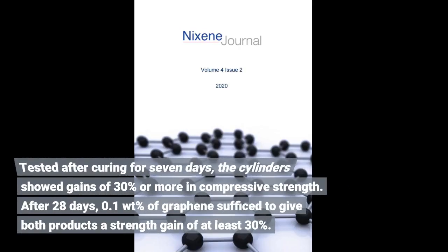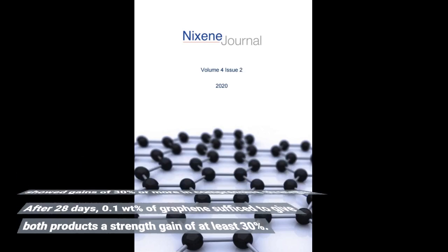Tested after curing for 7 days, the cylinders showed gains of 30% or more in compressive strength. After 28 days, 0.1 Wt% of graphene sufficed to give both products a strength gain of at least 30%. This increase in strength is in part due to a seeding effect of 2D graphene for better growth of cement hydrate products, and in part due to a reinforcing effect at later stages, Shahsavari said.